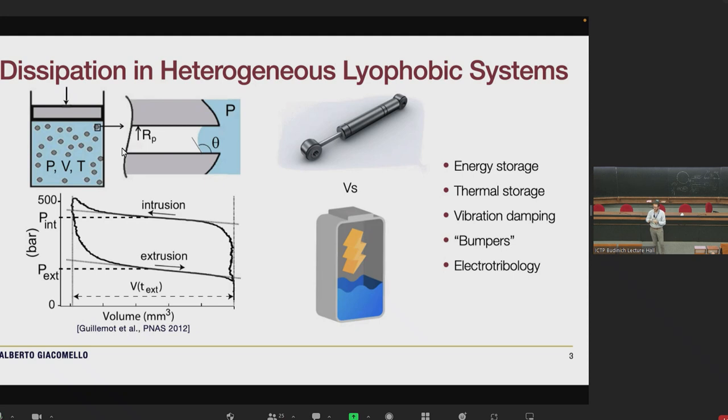You plot out curves similar to this. What you see is that because of hydrophobicity water enters into the pores only at relatively large pressure, in this special case on the order of 50 megapascals. You have this intrusion pressure. Once all the nanopores are wet, in order to extrude water you have to form a new phase which generally occurs at lower pressures. These two intrusion-extrusion pressures define a hysteresis cycle which of course gives rise to dissipation.